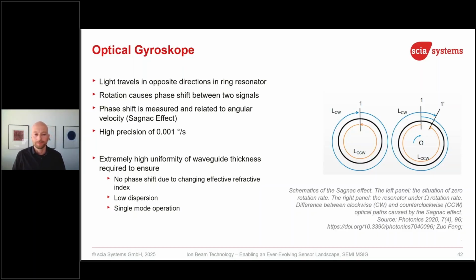angular velocity. The challenge now is that in order to make such good gyroscopes, you need extremely uniform waveguides. Uniform means regarding thickness. You have a few 100 nanometer thick waveguide, and then you need maybe 1 nanometer non-uniformity. And that's sometimes difficult. If you don't get it right, you might have a phase shift due to a changing effective refractive index. Dispersion is changing if it's too thick. And of course, you also want single mode operation for your laser, not multiple modes. So the dimensions have to be controlled very precisely. Luckily, we just learned ion beam trimming could be used to correct dimensional variations on a wafer.